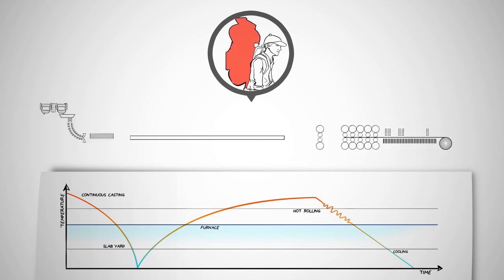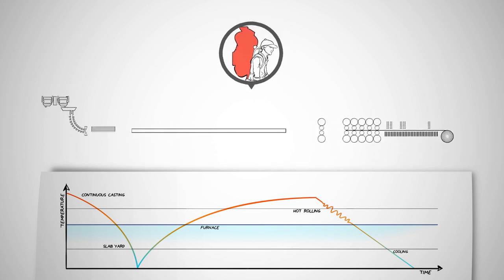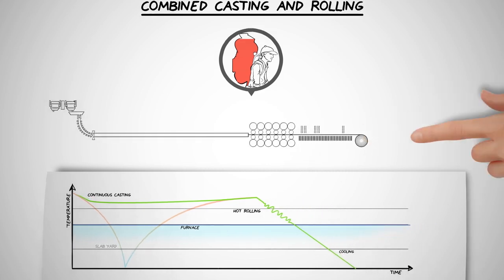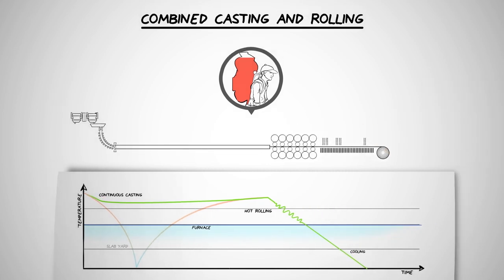Over the years, a number of combined casting and rolling plants have been built, but the traditional principle remained the same. For while it's true that the slabs do not cool down to room temperature, they are still rolled slab by slab in a so-called batch process, during which the temperature is subject to certain fluctuations that can only be compensated for by over-alloying. This constitutes a slight improvement, but as there is only one rolling step, the total control freedom offered by thermomechanical rolling is lost.